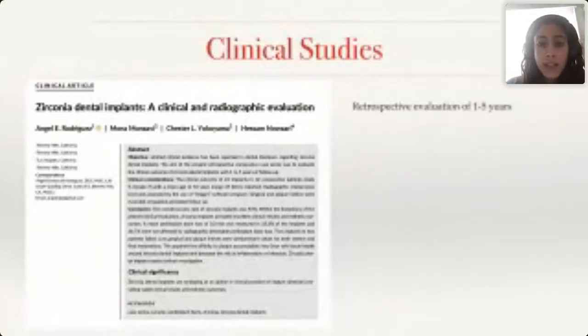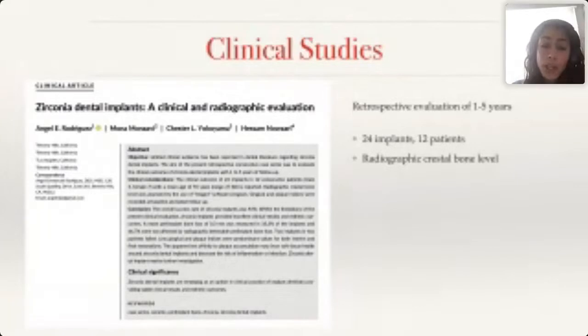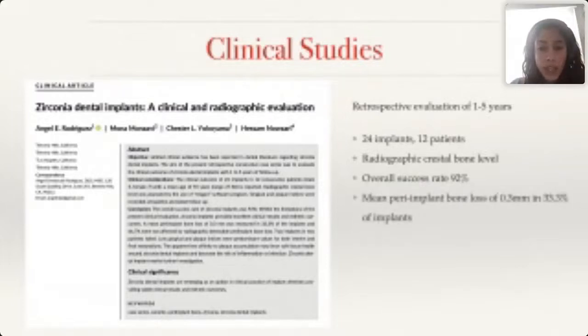It was a retrospective evaluation of 1 to 5 years, with 24 implants in 12 patients. We evaluated the radiographic crestal bone level using ImageJ software. We had a high success rate of 92%. The mean peri-implant bone loss was only about 0.3 millimeters in only 33.3% of the implants, so about 70% were not much affected by bone loss.